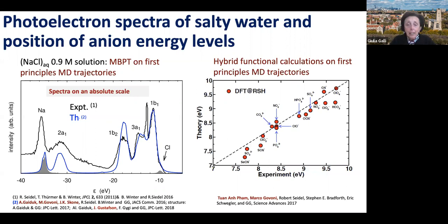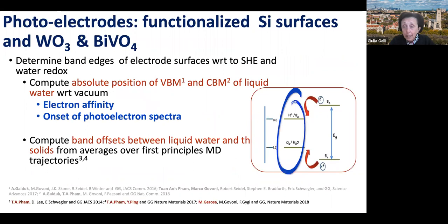So, you know, in some cases, the errors are smaller, but they are qualitatively good, not quantitatively excellent. That's okay. So now we have these levels from a theoretical point of view, and then we can do a calculation of our interface, use our favorite method to calculate the levels at the interface, and we can align them with water, and we can understand what happens. So now let me show you three examples. One about silicon surfaces, which have been used with certain functionalization as photocathodes in photoelectrochemical cells, and two about tungsten oxide and bismuth vanadate, which have been used as a photoanode in photoelectrochemical cells. And let me tell you what we learned, okay?